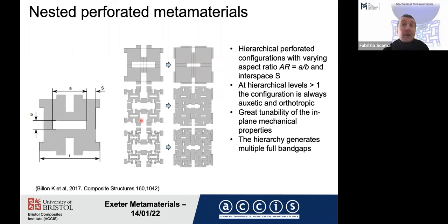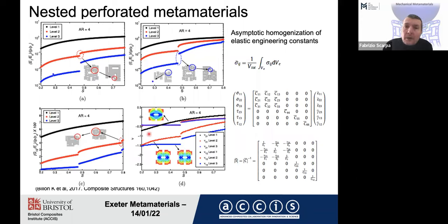And this configuration actually has some interesting mechanical characteristics compared to the baseline one. First of all, the baseline one, or level one, is an auxetic metamaterial, but when you go especially to large interspace distances between the different perforations, we are talking about a parameter S that goes from 0 to 1, the interspace between the perforations, the configuration tends to go towards a sort of zero Poisson's ratio effect. Every time that we adopt a hierarchical configuration, we always obtain a negative Poisson's ratio configuration, spatially orthotropic, but always